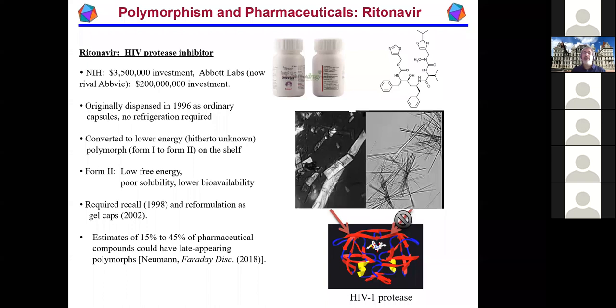You'd like to be able to anticipate when this is going to happen before it does, so that you avoid this problem. And it's been suggested, actually as recently as 2018, that somewhere between 15 and 45% of pharmaceutical compounds could have these late-appearing polymorphs, right? Now, doing the crystallization experiments that you need to find all of these polymorphs and to figure out their free energy ranking, especially when some of them are late-appearing polymorphs, is an extremely difficult thing to do, all right? So in material science, this is an outstanding challenge, right?